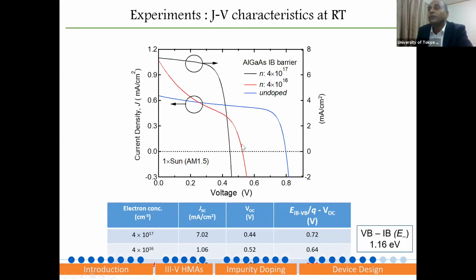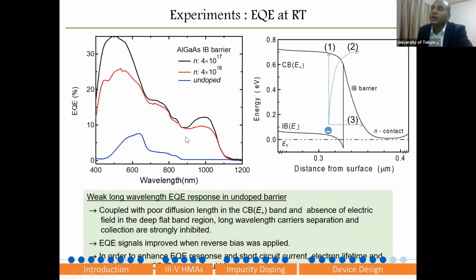If you have a very highly doped material in your barrier layer, my open circuit voltage is very, very low, because I am missing my voltage. As I told you, there is a lot of tunneling leakage. But if the carrier concentration is a little bit lower, 4 times 10 to the power 16, you can improve the open circuit voltage. And if you have a very thick barrier, the electron cannot pass through, so you see a very high voltage. So what I'm trying to tell you is that we have to stop the tunneling leakage of the intermediate band. This is my summary of how we can stop the long wavelength photon leaking through tunneling.